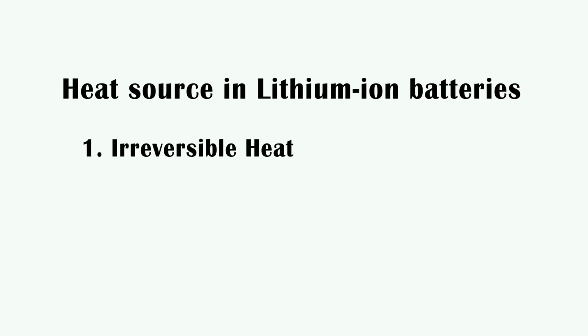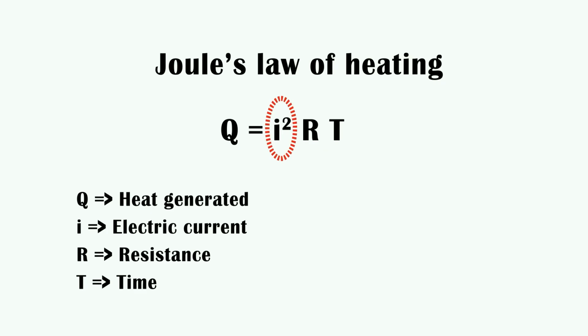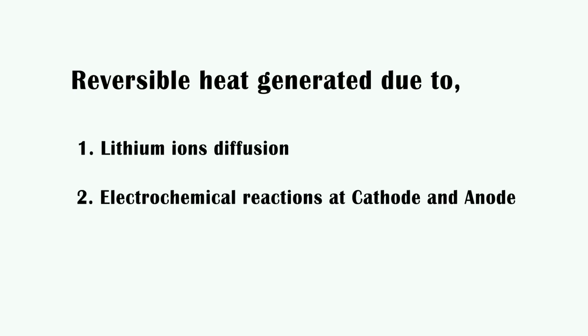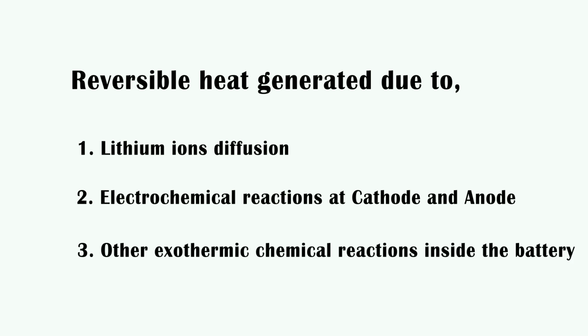The heat generated in lithium-ion batteries can be divided into two parts: one, irreversible heat, and the other, reversible heat. Irreversible heat is generated in lithium-ion batteries due to the Joule effect according to the equation, that is, upon fast charging with high current or upon high internal resistance of the batteries. Whereas reversible heat is generated due to the diffusion of the lithium ions, due to the chemical reactions in the cathode and anode,